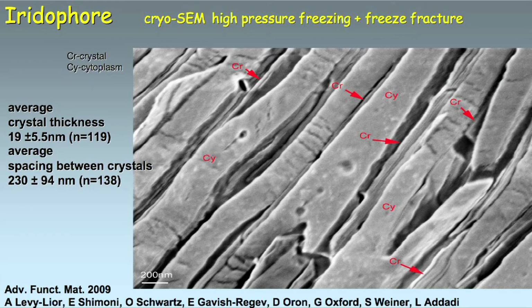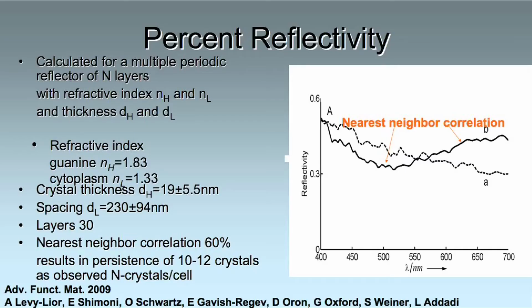And now we can, in fact, get all the numbers that we want. Again, these are the thin crystals. So you can see the edge of the crystals here, and this is the cytoplasm, the cellular water-based material that separates between the crystals. And the measurements tell us that the average crystal thickness is 19 nanometers. So really, really very thin. And we can evaluate the average spacing between the crystals, such that now we are well armed with all the data that we need in order to simulate and understand the reflectivity profile.